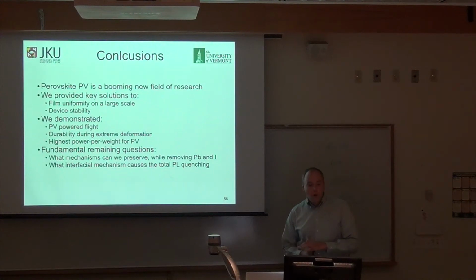And really, what mechanisms can we preserve from the perovskite material? Which are the key mechanisms that cause the solar cells to work well? What can we preserve when we replace the lead and the iodine? Because the iodine is going to be sensitive to water no matter what, and the lead is going to be toxic no matter what. We want to get rid of both of them if we can, but we might not be able to.